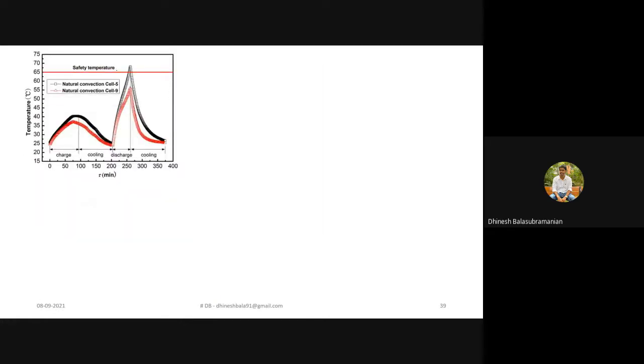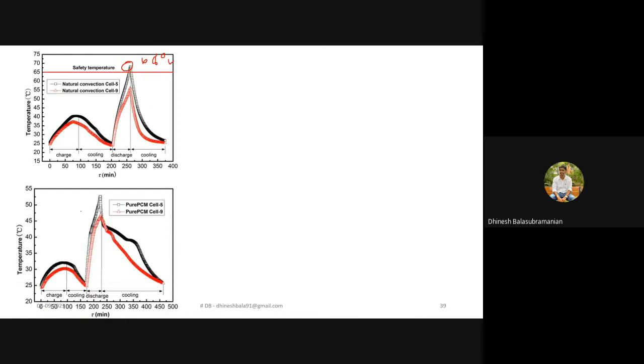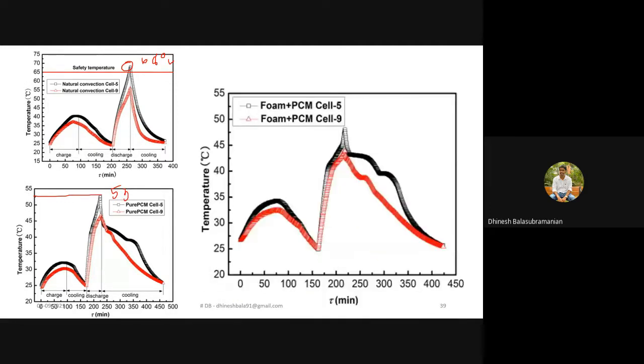If you make use of air as a medium, the cell number 5 temperature would be 68 degrees Celsius for this particular case study. And if you are able to pour PCM in between the batteries, you can try to step down the temperature from 68 to 53 degrees Celsius. And when you are able to combine PCM with metallic foam, you can even further pull down the temperature from 53 degrees Celsius to 48 degrees Celsius.